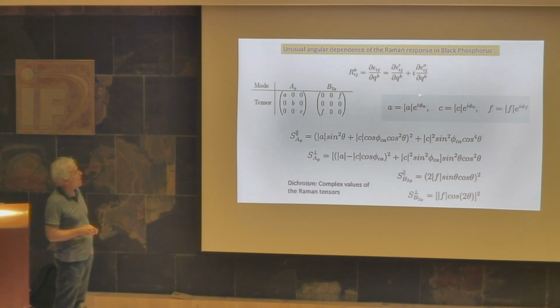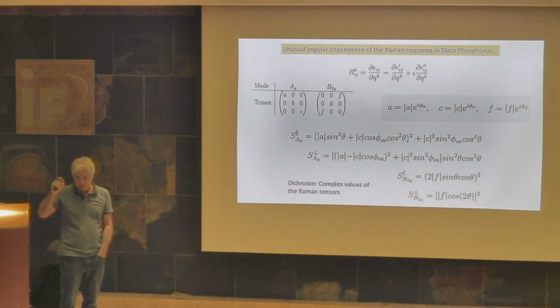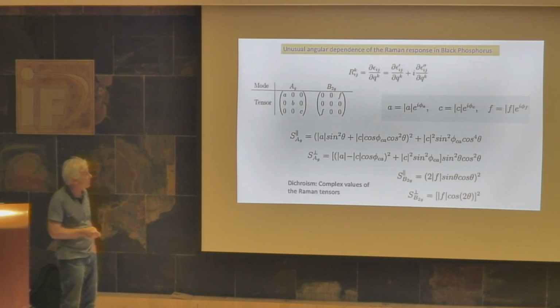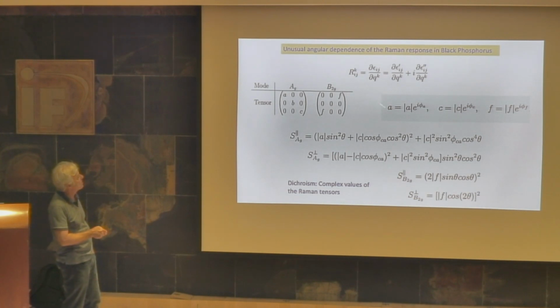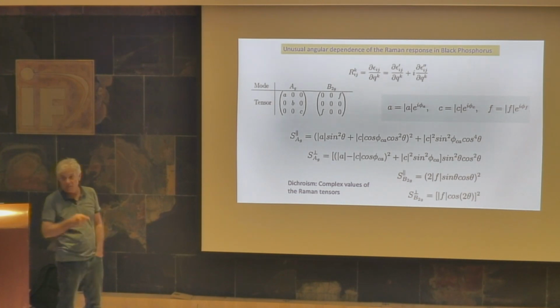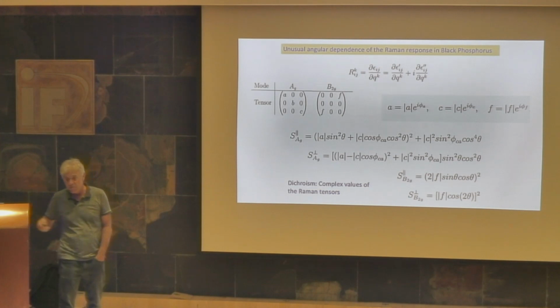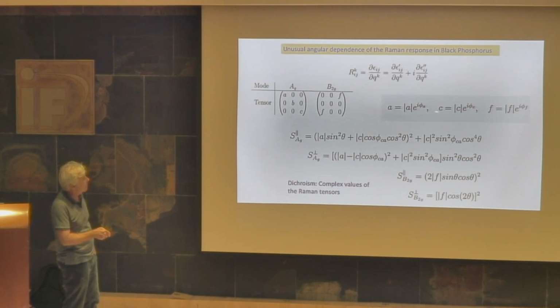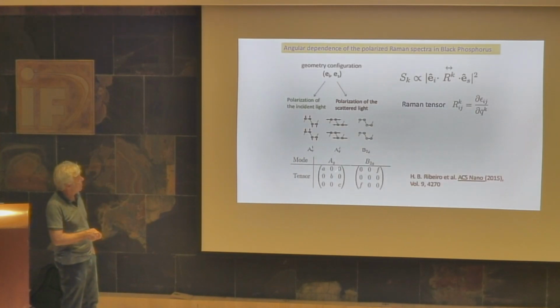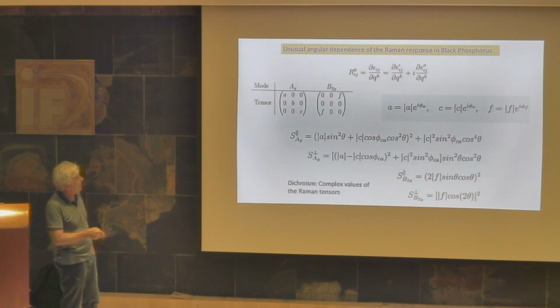In fact, what we realized in this work is that if you consider Raman tensor elements only with real components, you cannot fit the data. But we realized that the Raman tensor is a complex number with a real and imaginary part, with one amplitude and phase. Then, if we put those Raman tensors for the AG mode and B2G mode in this expression,